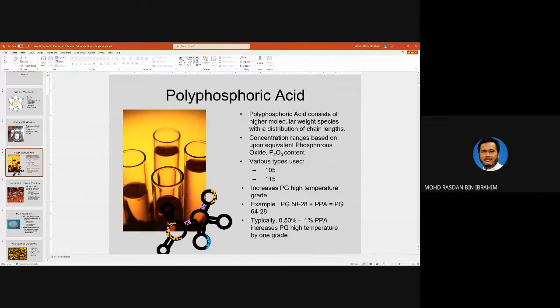PG grade is another standard of classifying bitumen. In our previous class, I mentioned that the usual method that we use to classify our bitumen in Malaysia is using penetration grade, where it can be penetration grade 80 over 100 or 60 over 70. But in America and also in some companies in Malaysia, they use PG grade, performance grade bitumen. For example, PG 58 dash 28 means it is performance grade to be used at a maximum pavement temperature of 58 degrees, and the lowest temperature recommended for using that bitumen is negative 28.